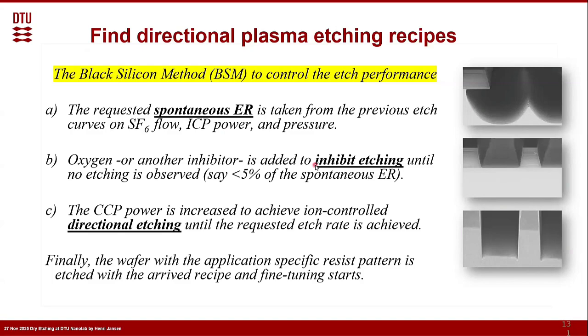Then the next step is, you add an inhibitor. So inside your SF6 plasma, you add oxygen or another inhibitor, it can be C4F8, until you see that the etching has totally stopped. So in the beginning, it will be slower and slower and less undercut, and there's a moment where everything stops.